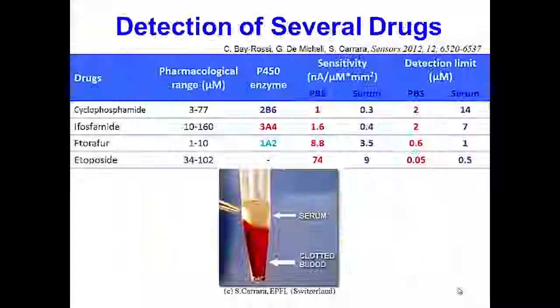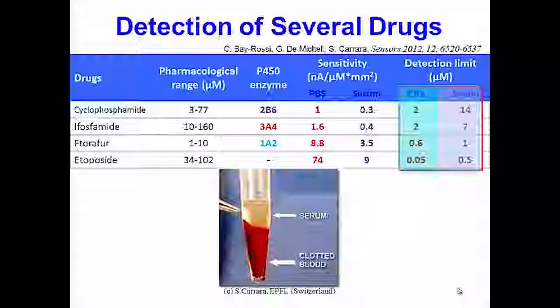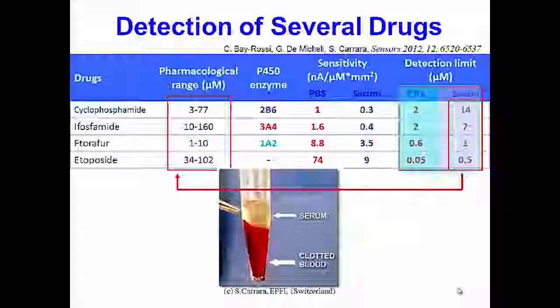And to demonstrate that, we moved from PBS to human blood, especially to human serum, which is what remains of the blood when we remove all the cells. And as expected, you can see we lost in terms of limit of detection. The cyclophosphamide moved from 2 micromolar up to 14 micromolar. We lost almost one order of magnitude moving from a lab sample to a sample of human blood. However, luckily for us, the new limit of detection still enables us to address the expected pharmacological range in human blood. And we repeated that not only for cyclophosphamide, but also for 3 other important anti-cancer compounds like ifosfamide, ftorafur, and etoposide.